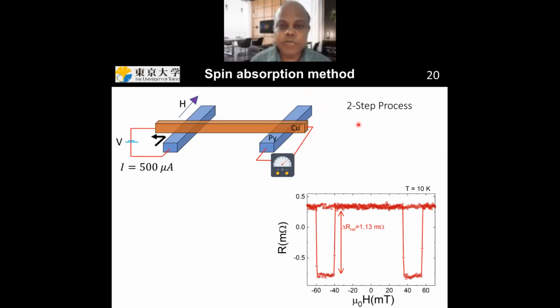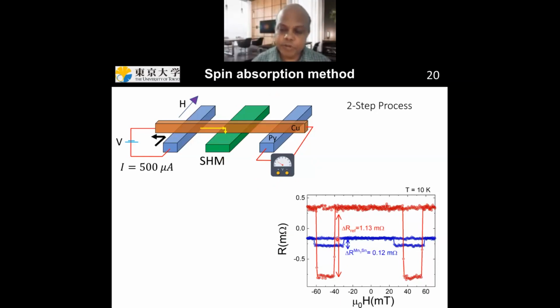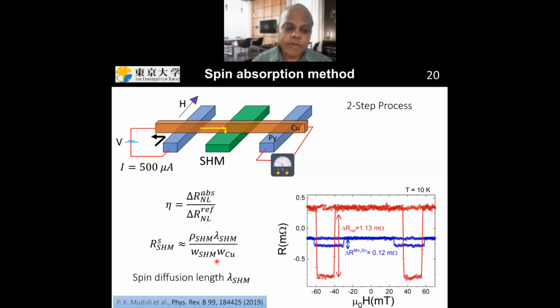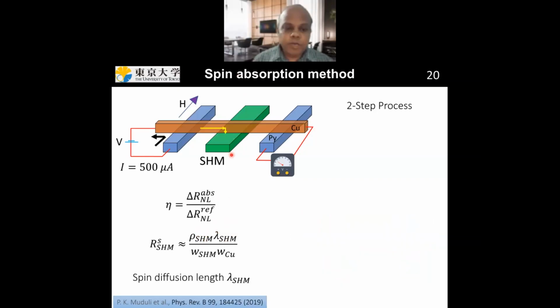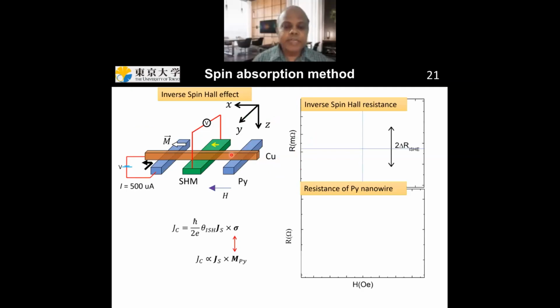In the first step, you demonstrate spin absorption. In the second step, you measure the spin Hall effect. So in the first step, to demonstrate spin absorption, you measure the spin signal, which looks something like this over here. Now, if you put a spin Hall material in the middle, some of the spin current will be absorbed by the spin Hall material. So if you measure the spin signal again, then you will see that the spin signal is reduced. And now if you calculate the ratio between the two spin signals, then you can calculate the spin resistance of your spin Hall material. And if you know the resistivity of the spin Hall material already, then you can calculate the spin diffusion length of your spin Hall material.